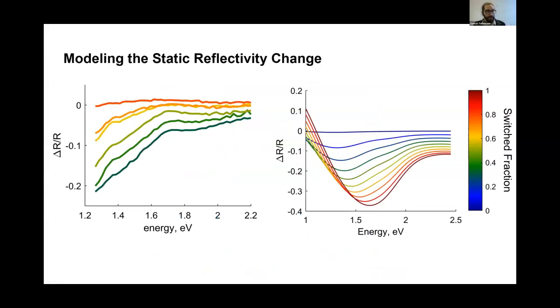So on the left, I've plotted experimental data. This is just reflectivity from a visible spectrometer taken as a function of the incoming laser fluence. So each of these reflectivity plots is the change in reflectivity as a function of fluence above the switching threshold. And on the right, what I'm plotting is the predicted change in reflectivity as a function of essentially the switched fraction. So all I'm doing here is modeling the reflectivity of a thin film of LCMO on our substrate with some fraction having a dielectric function that looks like the insulating LCMO and some fraction that has a dielectric function which looks like the metallic LCMO. And what you can see is that these quantitatively reproduce our experimental results, and they agree with the terahertz spectroscopy.